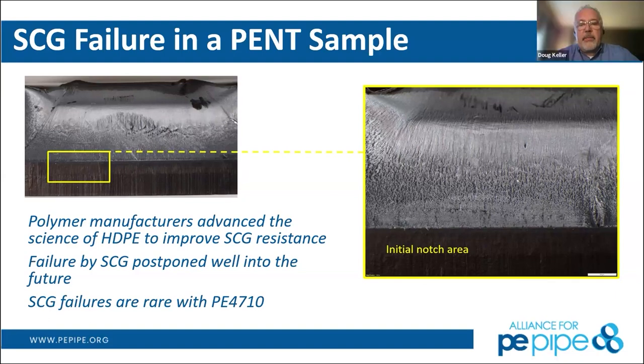So the PENT test really came about in looking at gas mains, and that's where the work initially was done because some materials produced in the 70s were showing premature failures in gas mains, and that's where the PENT test was developed to replicate the type of failure mode that they were seeing in gas mains. And at the time, those materials were testing at about 1 hour of PENT. And again, as I said, modern materials today, 4th generation materials, are in the 2,000 to 10,000 hour range.